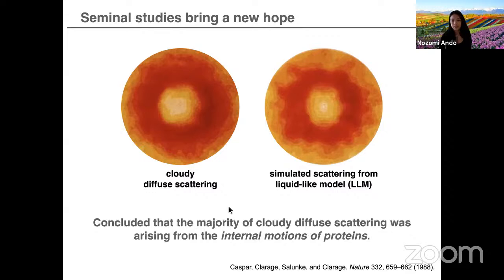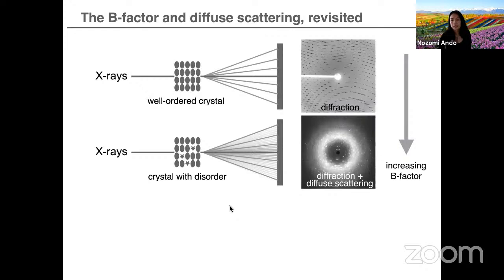And in terms of key ideas that have come out in the past few decades, another one has to do with the relationship between the B factor and diffuse scattering. So I'll show you, here are two schematics. This one I already showed you before, which is if you have a well-ordered crystal, then you only get constructive interference, you get the diffraction spots. Now, if you have any sort of disorder in the crystal, then what happens is that the X-rays don't go where they're supposed to go. Instead, they go in between. And this is what gives rise to the diffuse scattering.